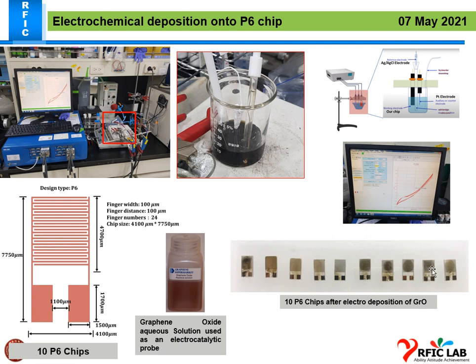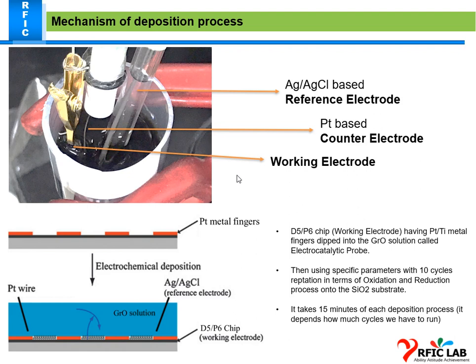So it looks like a linear, ultra thin film of graphene oxide, and it is much stronger than spin coating and dip coating. That's why I'm preferring this one. And it's a clear picture of all the electrodes. As I already mentioned, this Ag/AgCl is the reference electrode and Pt is the counter, and our P6 chip is dipped into the solution. The solution is graphene oxide, so our chip acts like a working electrode.